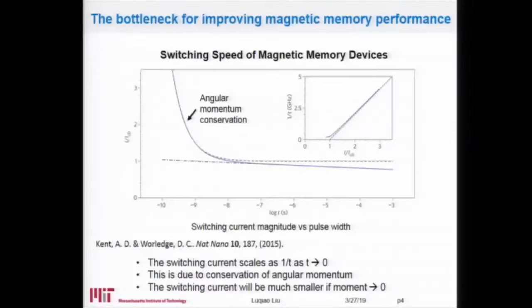So what's the bottleneck? Why can we not write information very quickly into those magnetic memories? It turns out that it's governed by some very fundamental physics laws, as explained by this curve. In this figure, the y-axis is the switching current, while the x-axis is the switching time in log scale. So -8 corresponds to 10 nanoseconds, and -9 corresponds to 1 nanosecond. As you can see, as you reduce the switching time below 10^-8 seconds, 10 nanoseconds, the switching current becomes significantly large.